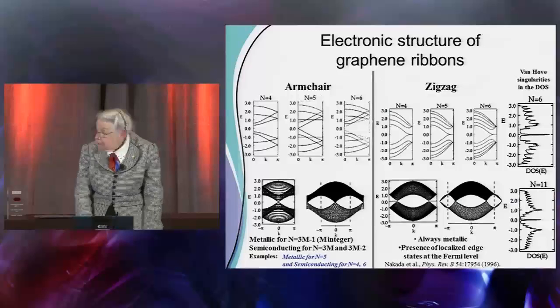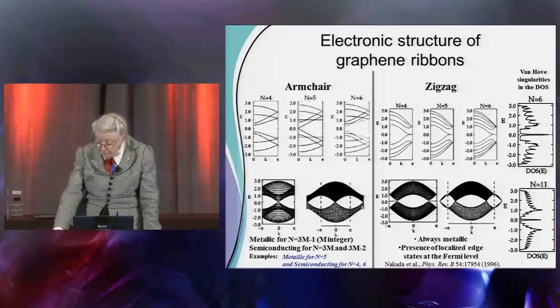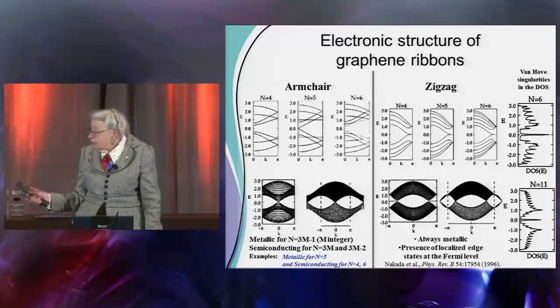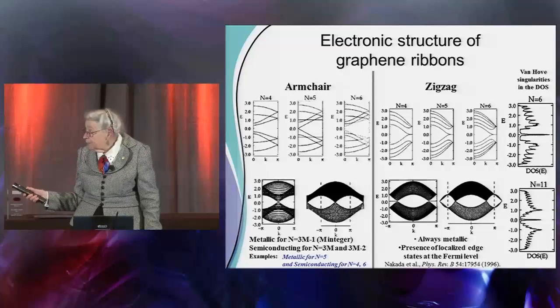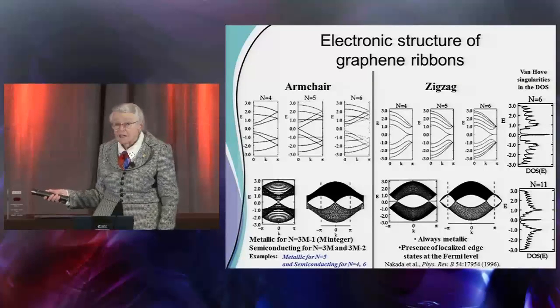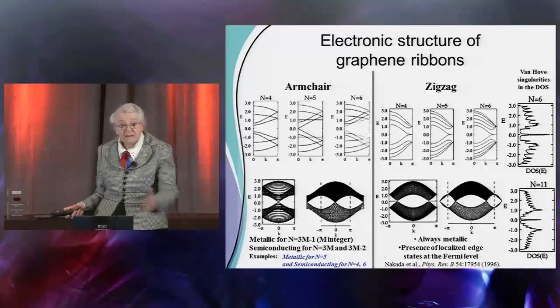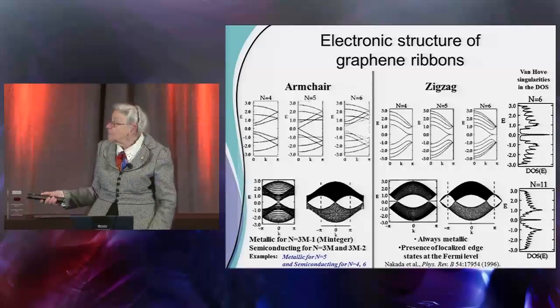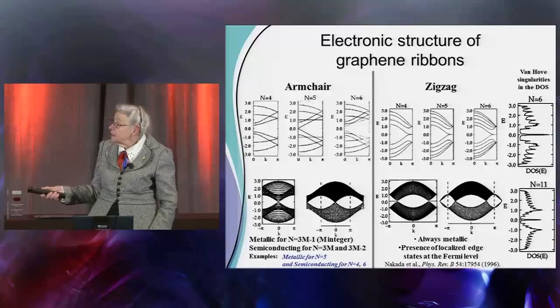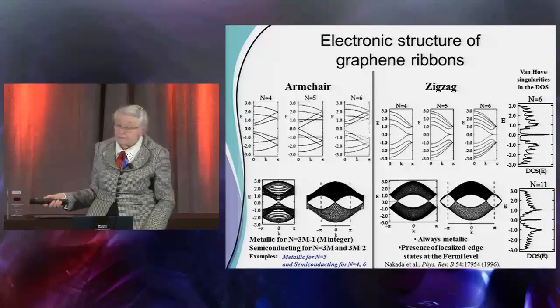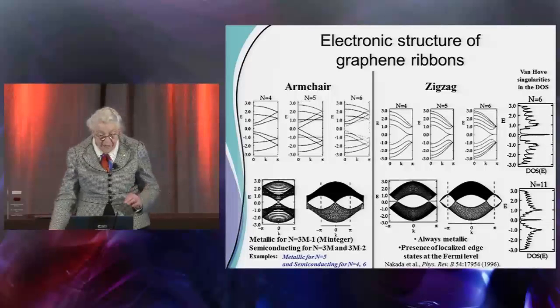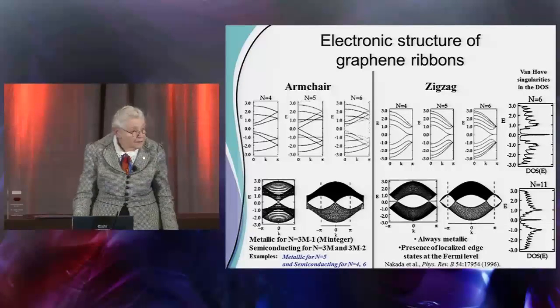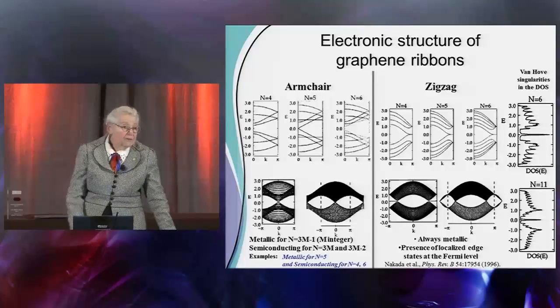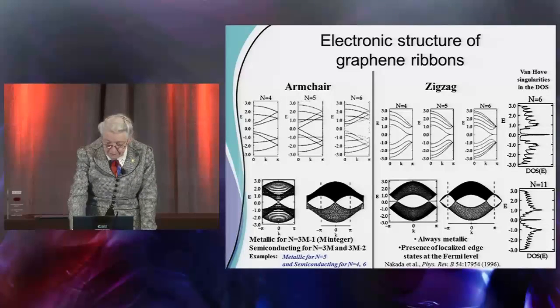And so what's of interest is that a zigzag ribbon will have a very high density of states at the Fermi level. And independent of the diameter, they all have that property. But the armchair are like nanotubes. They could be either metallic or semiconducting, depending on the width of the ribbon. And you can control that and actually measure that. So you can make the ribbon that you like and sustain it and see what the properties are.